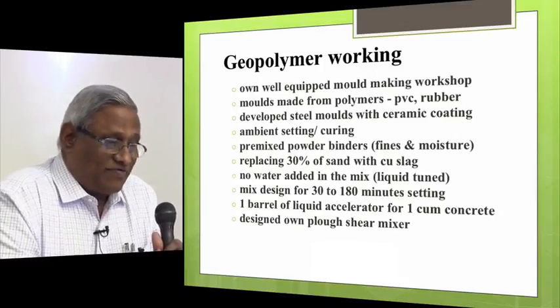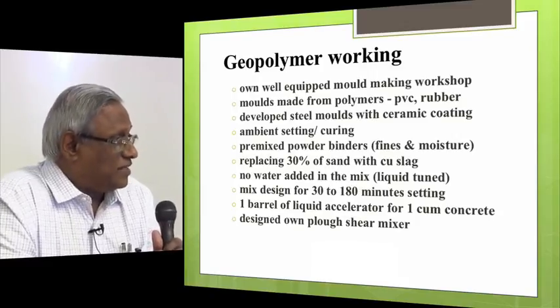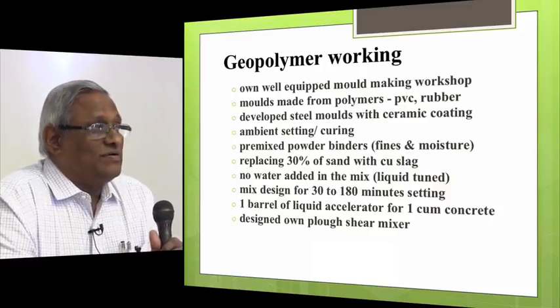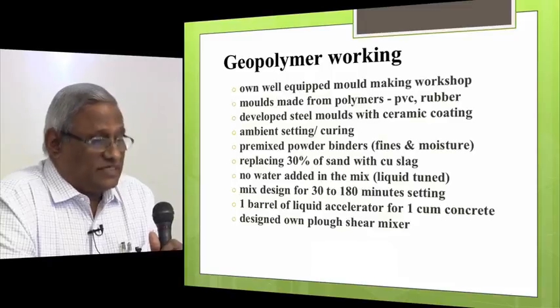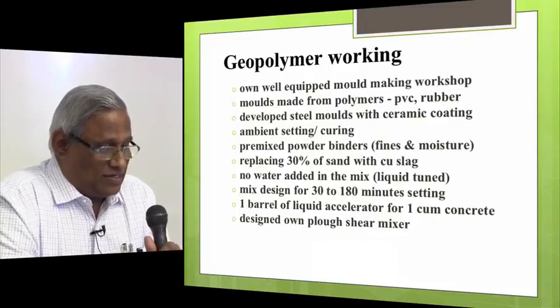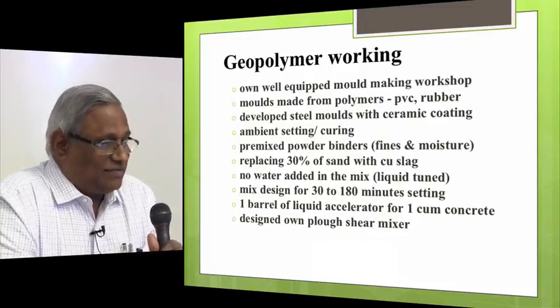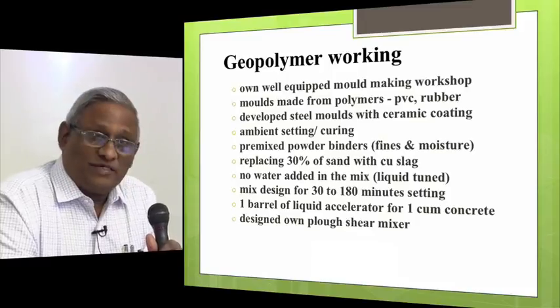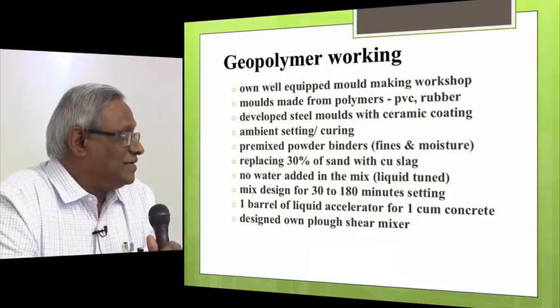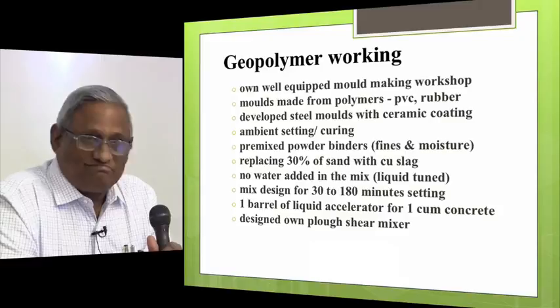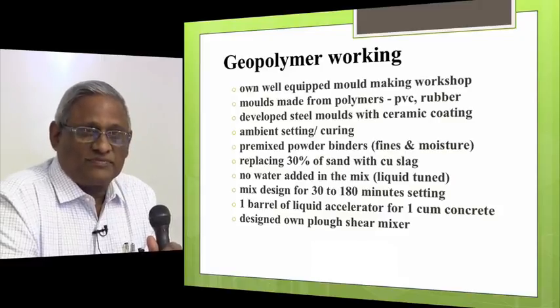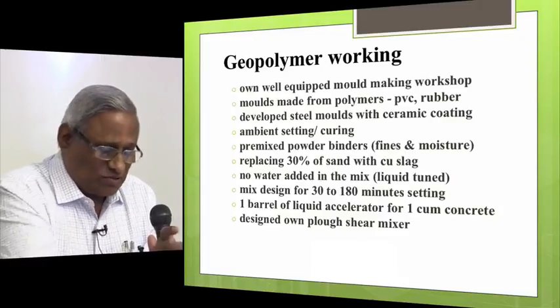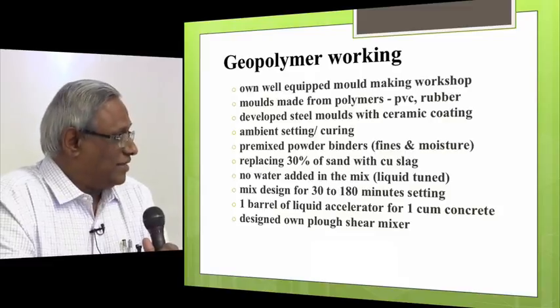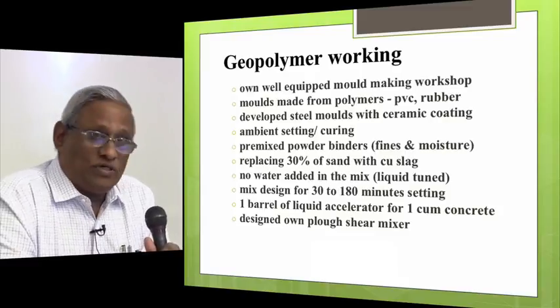And we have a plant for manufacturing pre-mixed powder binders in a lot of mix ratios of fly ash and GGBS. The issue here is two things. If there are more fines, it consumes more accelerator. And if there is more moisture, then it's very difficult to control. So these are the two things we need to address when doing the pre-packing of powders.